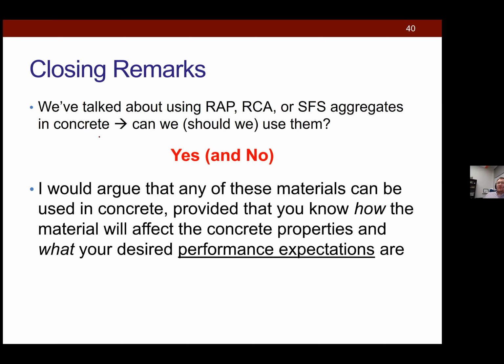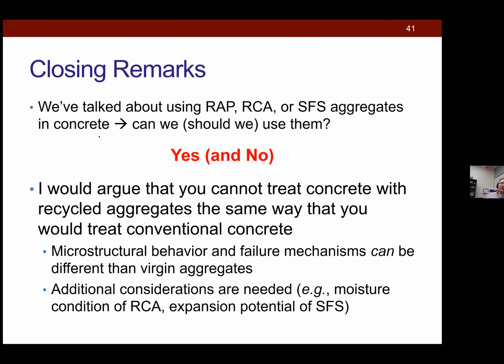But you need to adjust your performance expectations, right? Concrete with recycled aggregates is not going to behave the same way as conventional concrete. First of all, as long as you know that and understand that, we might be able to come to a better consensus on how to use these. So again, you can't treat these materials the same. All right, the failure modes are different. Okay, the microstructural behavior is different, right? We talked about how cracks in concrete with RAP are still going to propagate through asphalt cohesion, right? It's going to propagate through the asphalt film. That's not something we really have to worry about with, let's say, a limestone aggregate, a granite aggregate, right?